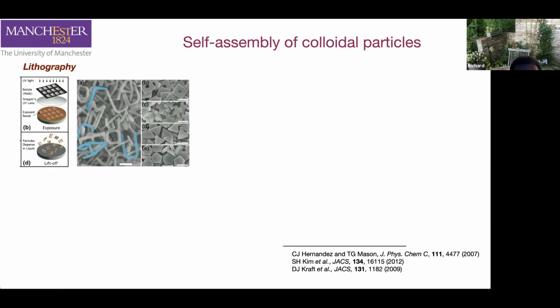Okay, that's much larger than what I was thinking. Okay, thanks. The system that I showed you in collaboration with Chekesha Liddell, the size of those particles is about 100 nanometers, the ones with the spherical caps and so on. The second question is, can this smectic colloidal ring be locked into its shape, then dried by sintering? Well, that's a very interesting question, and I don't know. There have been some reports nowadays of these rings that I was mentioning before, but so far nobody has been able to observe the smectic phase.